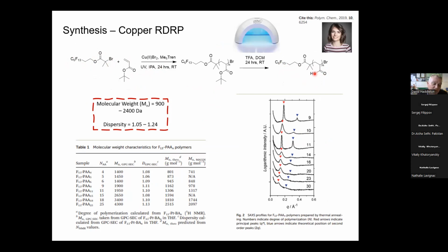Because this chemistry, I know you probably won't all believe me, but because this chemistry really does give you the most precise control over the length that you can get, then DP5 and DP6 and DP11 are distinguishable. So 5 and 10 are completely different. If you use most living radical polymerizations, well, first of all, you can't make DP5. And if you could, you couldn't distinguish between 5 and 10 or 20 and 25. It's just too small. You can distinguish between 10 and 30. But what we're doing here is we get very, very narrow polymers. We get very discrete chain ends, and the dispersities are pretty much as low as you can get.